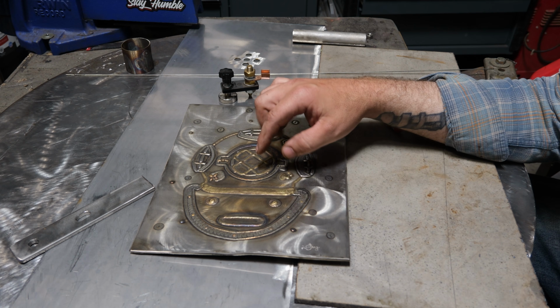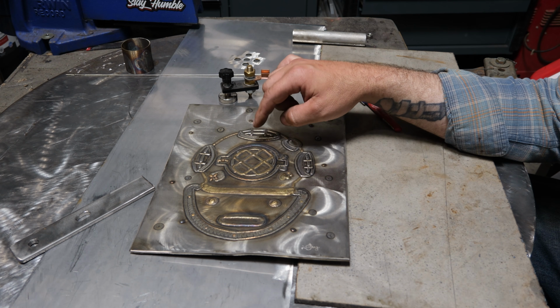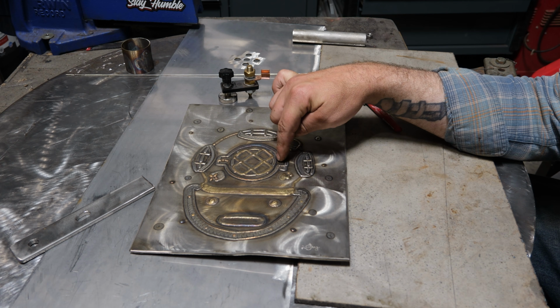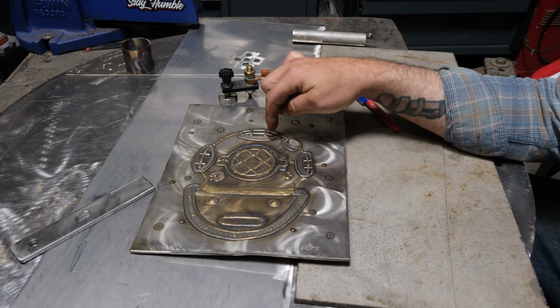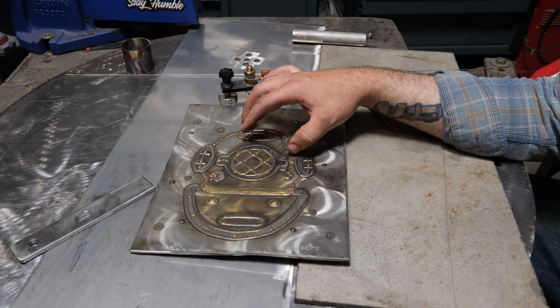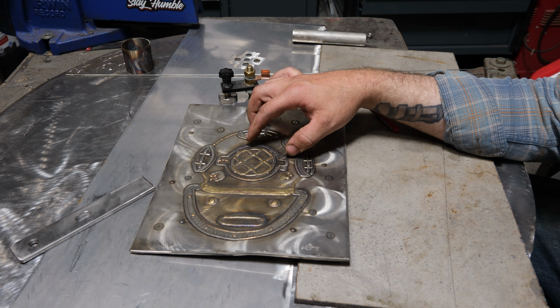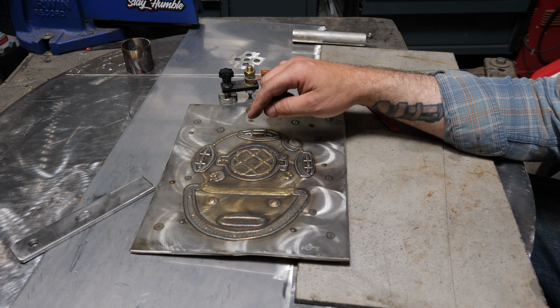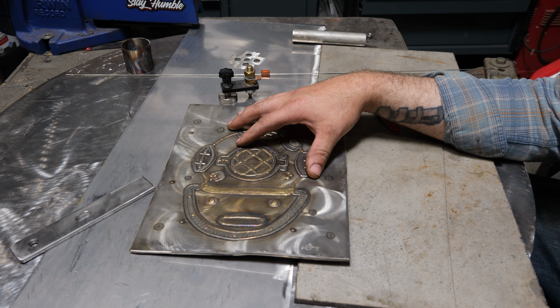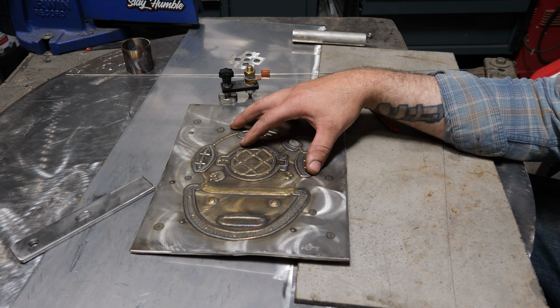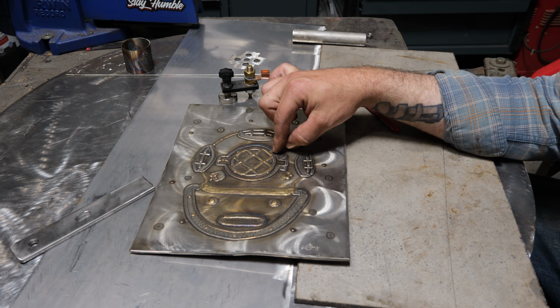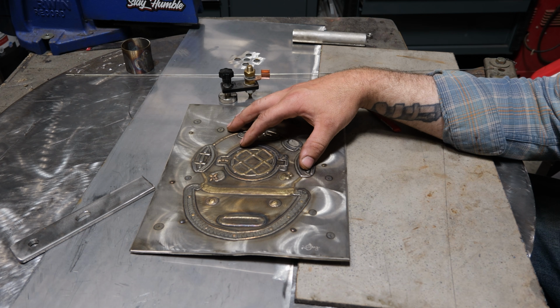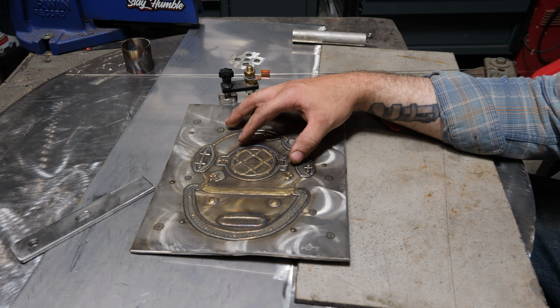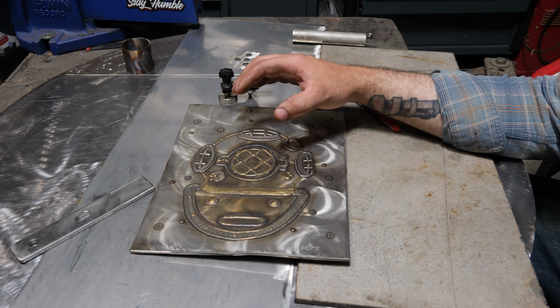Now, this gold stuff here is actually not stainless filler, that's silicon bronze. But when you look up here, this blue and the gold here, that's all oxidization. It's very common for people to think that any color on stainless steel means it's junk. That's simply not the case. Stainless steel is not like titanium, which is super reactive, where color on titanium means the material is compromised. Color and oxidization on stainless welds is not an indication that the weld is weak or the material is compromised. It is an indication that that metal was hot and it reacted with oxygen.